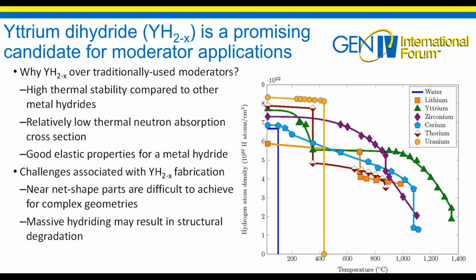The reason that we are researching yttrium dihydride is for its ability to retain hydrogen at higher temperatures than other moderator material. As shown in the figure to the right, where the hydrogen atom density is on the y-axis and the temperature on the x-axis, yttrium retains larger hydrogen concentrations at higher temperatures than the other material. As you can see, water is listed on the chart. We also have other types of hydrides that really drop their hydrogen concentration, meaning that the hydrogen diffuses out or we lose it from the material as the temperature heats up in the system.